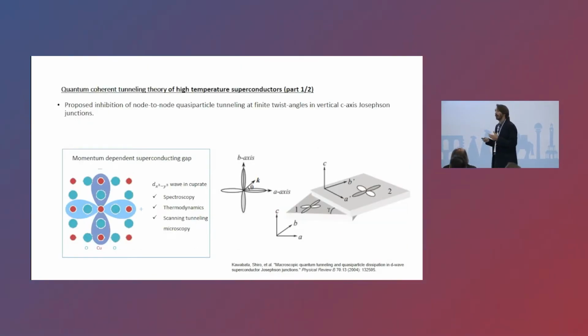Now, we know that the architecture is very important and can determine novel phenomena even if you play with the same material. It is known for a long time that cuprates, and especially BSCCO, as we have seen this morning, have d-wave gaps and d-wave order parameters, by spectroscopy, thermodynamics, and scanning tunneling microscopy. People have proposed and thought for a very long time about how to exploit these nodal properties of this material to create interesting systems. One aspect considered in the past is a proposed inhibition of node-to-node quasi-particle tunneling at finite twist angle along the vertical c-axis of the junction. This can lead to interesting macroscopic quantum tunneling phenomena.